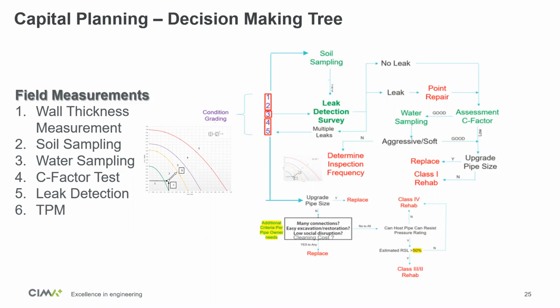Now, yes, there are some tools that have added value, in that in the same inspection run they can do remaining wall thickness and leak detection, for example the correlators based on acoustic technology. Other inspection tools will need two separate tools in order to do leak detection separately, and after that the remaining wall thickness. If we do an assessment and we don't find a leak, then I always recommend doing a C-factor assessment.